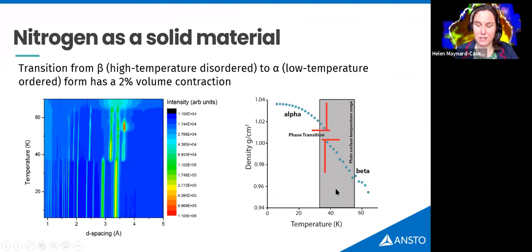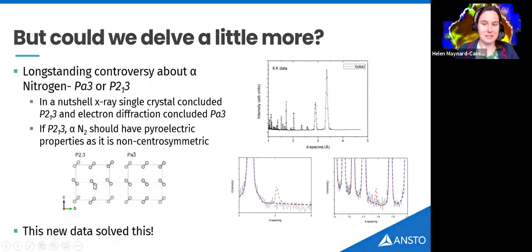But nitrogen is perhaps a little bit more interesting because it does have a phase transition over the seasonal variation of Pluto, and in this work we were the first to classify that density change. And you can see we go from the disordered high temperature beta form to an ordered alpha form as we cool down. And actually, you'd have thought by now we should know what the crystal structures of the elements are. No.